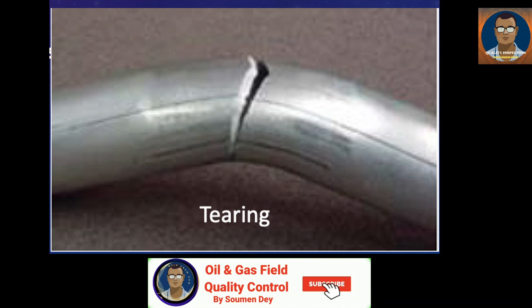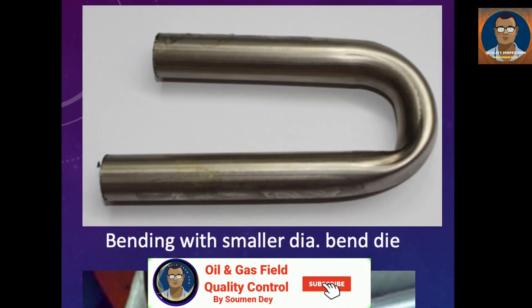Factors causing difficulties in bending: low wall thickness compared to tube diameter — when the ratio of wall thickness to tube diameter is small, fracture and wrinkling may occur on the tube walls. There is a limit to this ratio for every tube material. Low bending radius — changing the bend die diameter changes the bending radius. Bending with a low bending radius may be critical since there will be too much tension on the outer side and too much compression on the inner side, which can cause tearing or collapse on the outer side and wrinkling on the inner side.